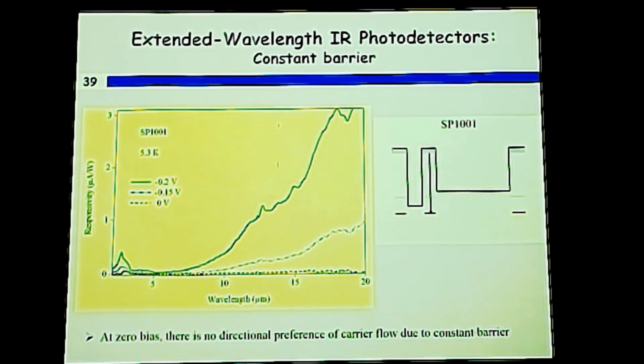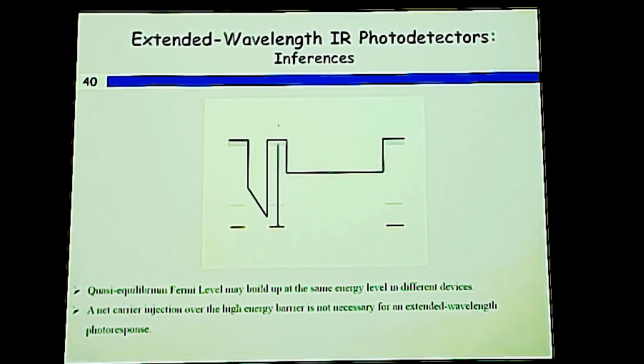So when there is no gradient or graded barrier there, we barely see any photoresponse at 0 volt, but when we apply bias, that starts to show up. So based on these results, what we can say is the quasi-equilibrium Fermi level that is necessary for the extended wavelength mechanism appears to be more or less fixed from device